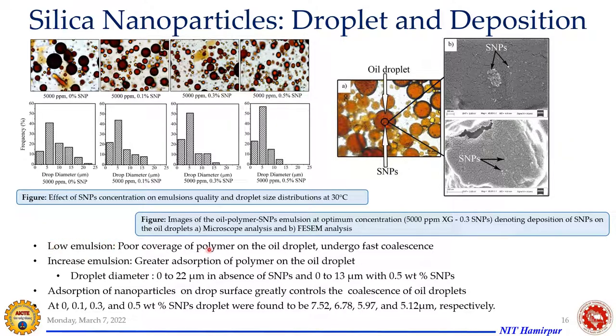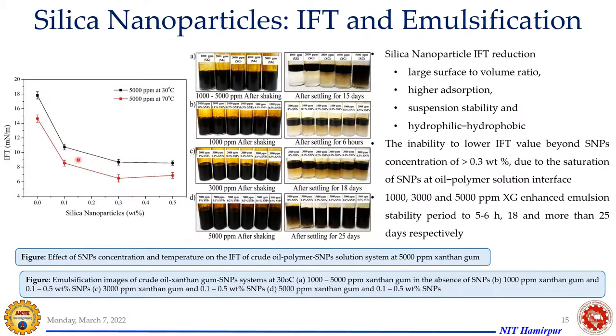And low emulsion stability means poor coverage of polymer on the droplet surface that undergoes fast coalescence. And to disturb this coalescence is why we are inducing these nanoparticles. And you can see here, these are stable forms. Okay. So we have also done this FESEM analysis, this is a microscopic image of the emulsion. And you can see how these nanoparticles are being spread over this oil water droplet surface. Okay. So this shows how the packing of nanoparticles on the oil droplet surface can improve the emulsification extent, can improve the interfacial tension reduction phenomena, and this has potential to recover crude oil to a greater extent as compared to your chemical EOR.